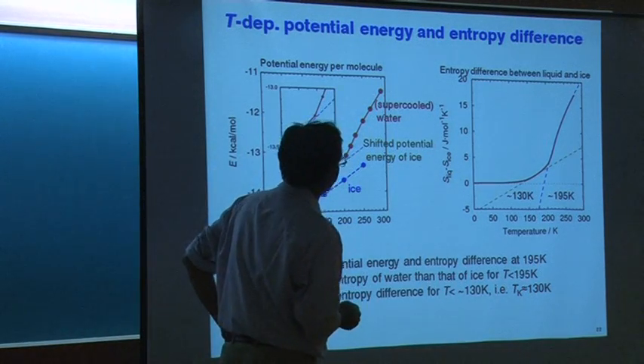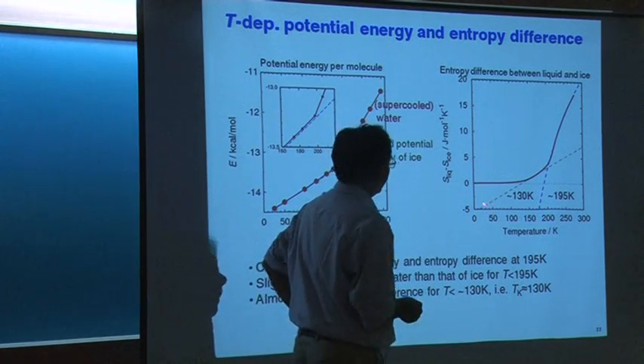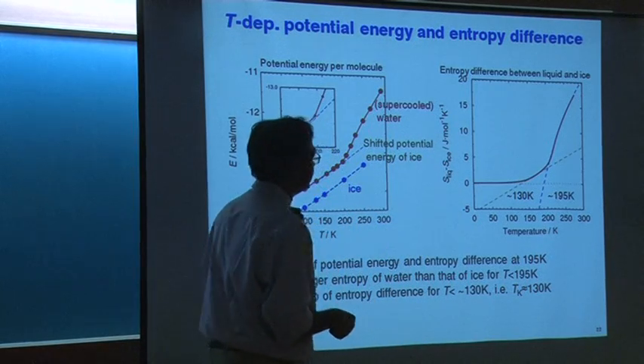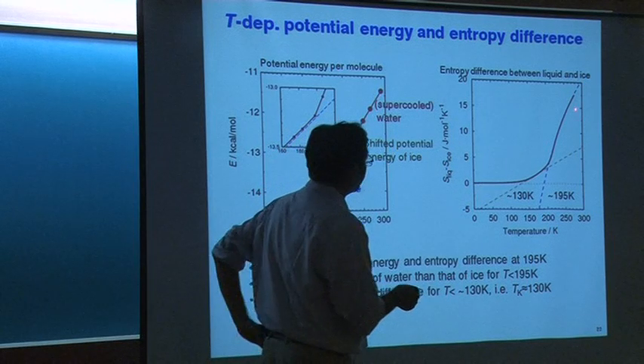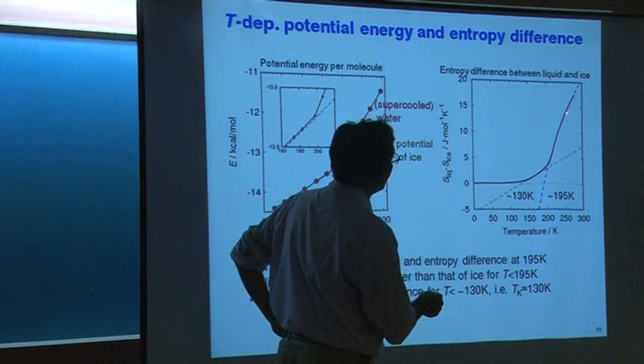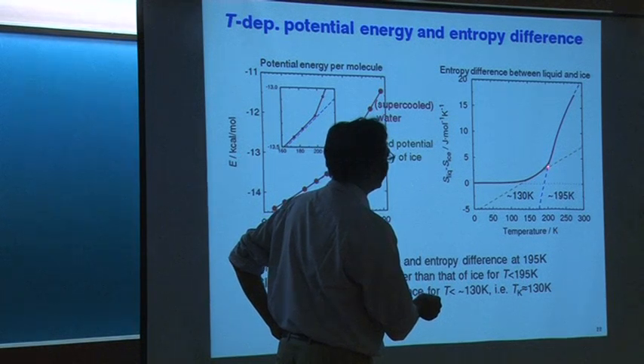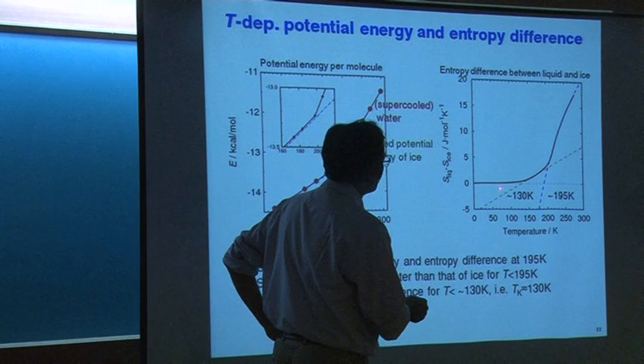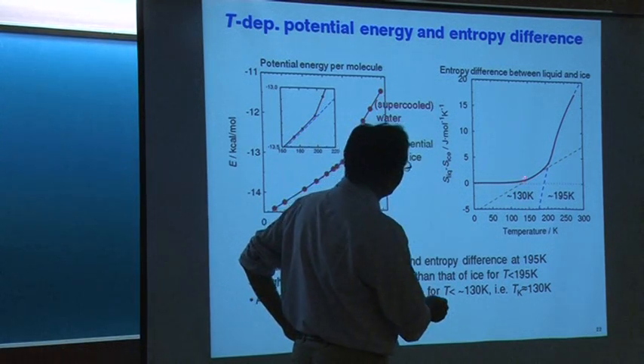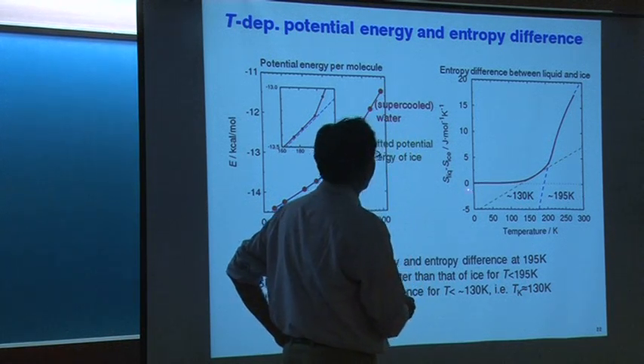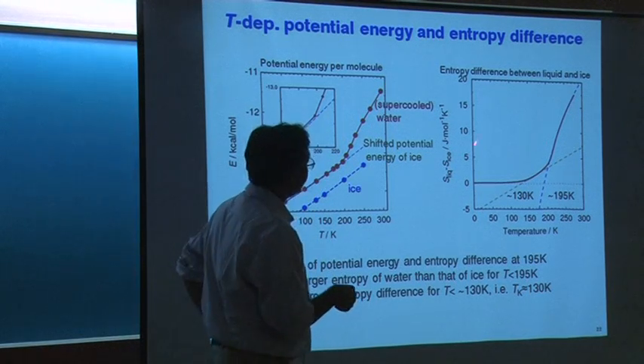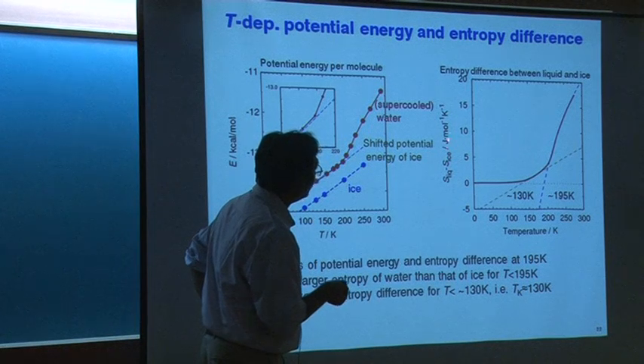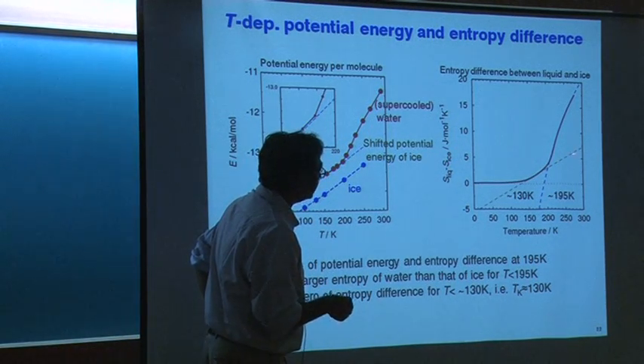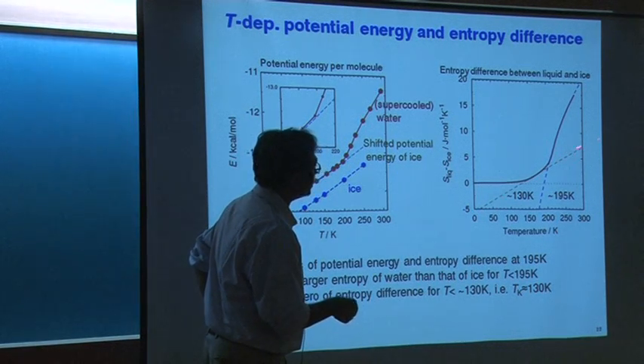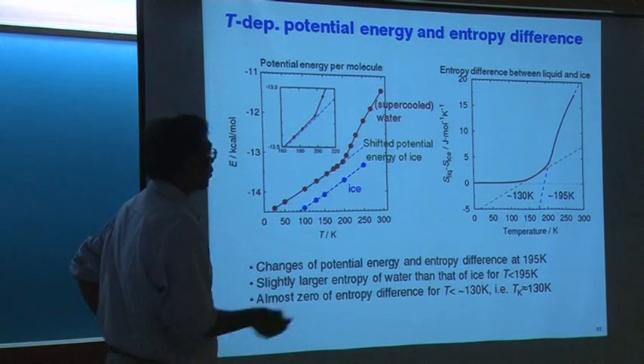Now look at the entropy. Entropy is very dramatic. It is a huge amount of calculation, taking 4-5 years to calculate the entropy. This is high temperature water coming and lowering temperature. Entropy starts to fall rapidly. Then it undergoes one crossover here, and then a second crossover here. Then at 110 Kelvin, maybe 120 Kelvin, the entropy of ice and the entropy of supercooled water or glass is the same. So this is the entropy of liquid minus entropy of ice in joule per mole per Kelvin. This we calculate, and we can measure it experimentally; it agrees completely, theory and experiment, and there is a lot of work to do that.